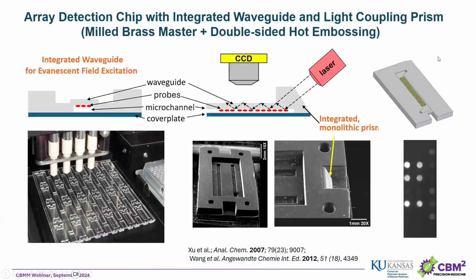The other example is, for example, the array chip with integrated waveguide and light coupling prism. This is a very nice example to show that you can not only make structures by micromilling that are different heights, but also that have different geometry, and everything is done in pretty much the same piece, in the same machining step, in the same piece of brass, and then transferred to the plastic.